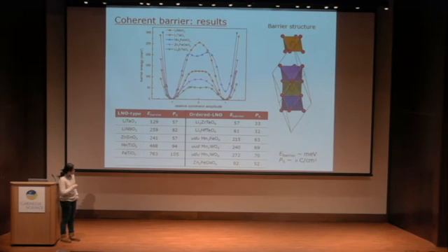And here this UDU is the magnetic state, because here we have magnet or iron. And this is the energy barrier, how the energy changes along the path. And you see, for most of the curves, the maximum energy is when the coordinate is equal to 0. That corresponds to this structure, this midpoint structure.